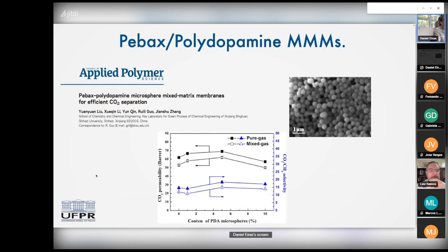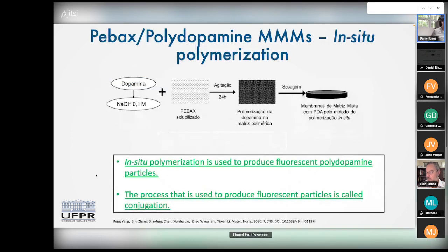So there have been some previous publications about the use of polydopamine for CO2 separation. They basically synthesized the polydopamine and added it to the polymer, incorporated it into the polymer. So what we did, instead of doing what we call ex situ polymerization, is we did in situ polymerization. So we combined the dopamine hydrochloride with